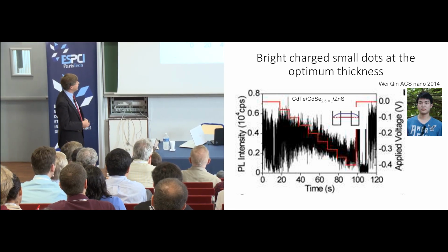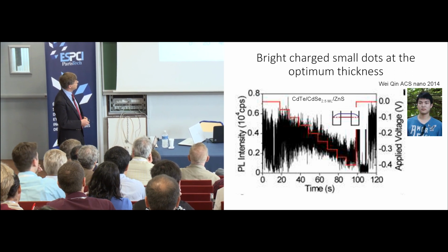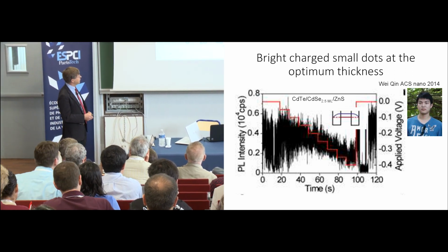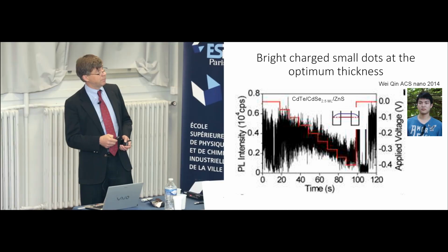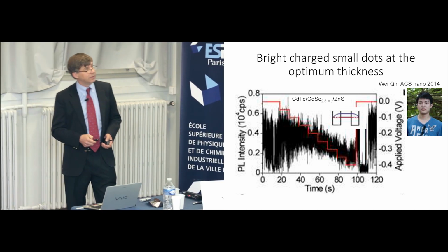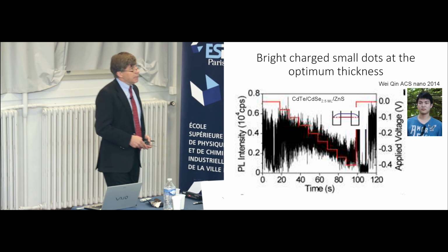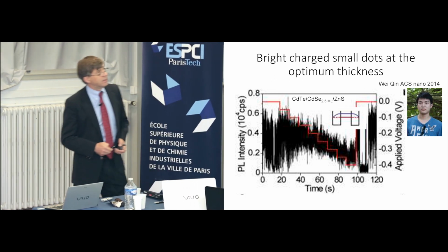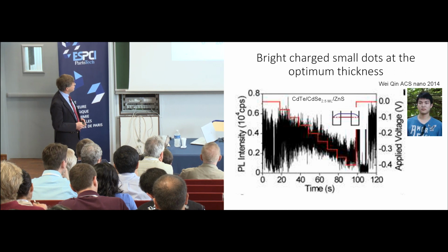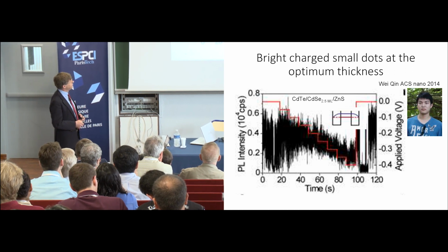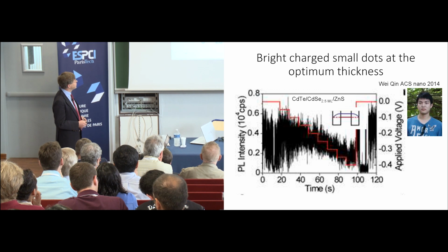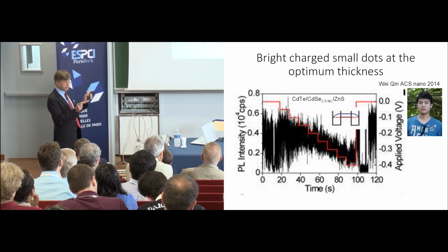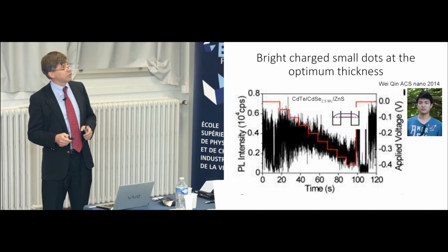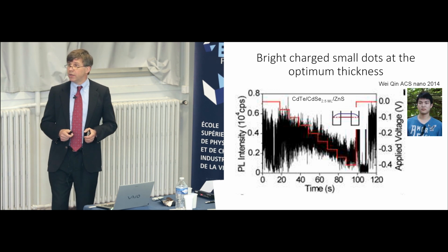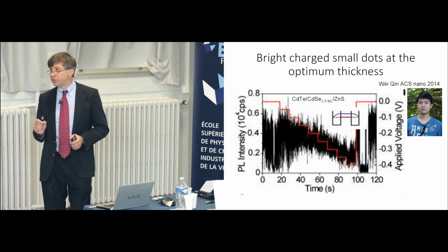So this was the blinking of a single dot, and then we stepwise make the potential reducing, and we find that it stops blinking. And it's more or less as bright as when it was in the neutral state, and then it comes back. Now, this is Wei Qin who did this work, a very brilliant young scientist. And so what we found was that it seemed as if this optimum in the trion lifetime was obtained when the shell is just big enough that the electron state is skimming the bottom of the conduction band of the core, which is where the electron has exactly zero kinetic energy in the core.